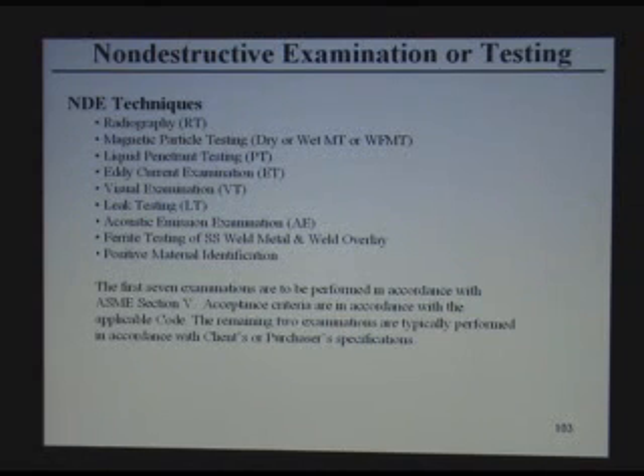These techniques include radiography, which is like taking an X-ray of your teeth to check the weld quality, and the code tells you what is acceptable and not acceptable. For example, cracks in welds are not acceptable; you have to cut it out and re-weld it. If you have porosity, there are some limits for porosity. Undercut has limits too. So radiography is used to ensure that the welding quality is good. Radiography can also be used to measure thickness: if you take a panoramic X-ray of a pipe from the side, it gives you the thickness of the pipe.